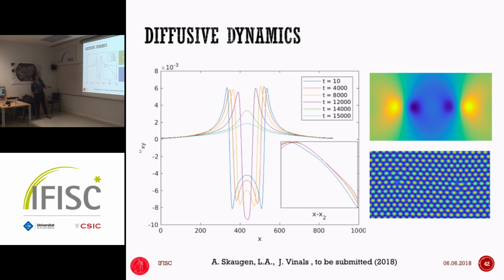So we start with initial times, and then you see those two peaks coming together. That's because they annihilate, and eventually it's going to dissipate, and then it's going to take a long time before this bump is going to go down to zero and you have perfect equilibrium. This is for the case when we have just diffusive dynamics, and if we look at the stress away from a dislocation,